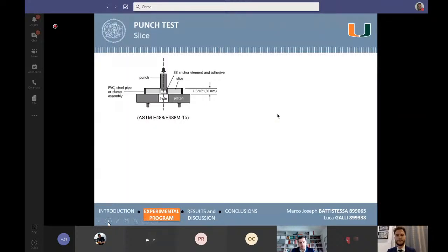Let's talk about the punch test, which is the methodology proposed in the previous thesis work to evaluate the effect of different environments on the adhesion between the GFRP and the concrete. This test is originally available in the American standard, but is used to test structural chemical anchors. Starting on this basis, it has been modified, trying to define a proper setup for the new purpose. The specimens, as you can see in the picture, are cylindrical slices, 3 cm thick and 15 cm in diameter.